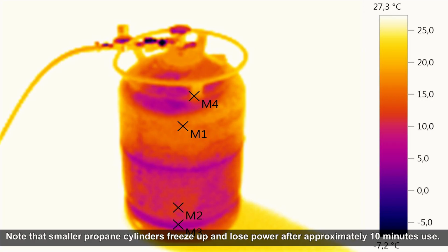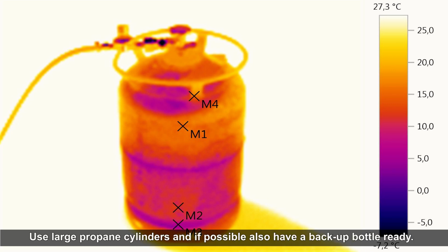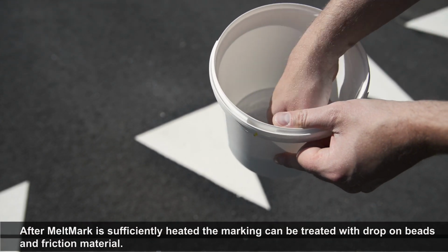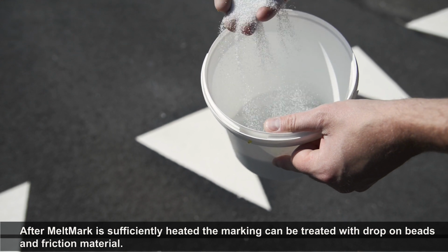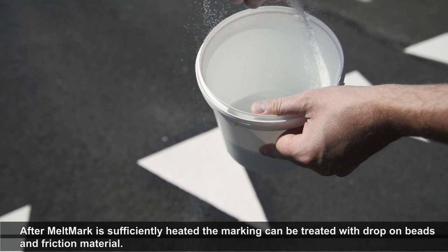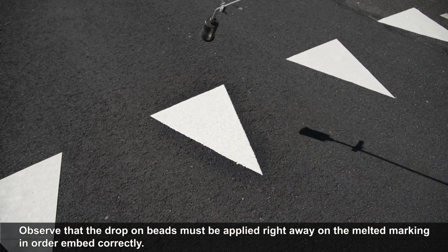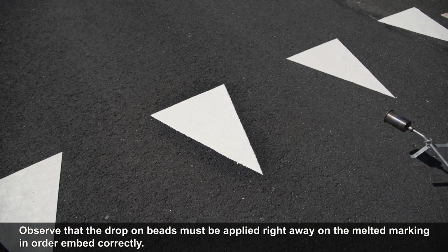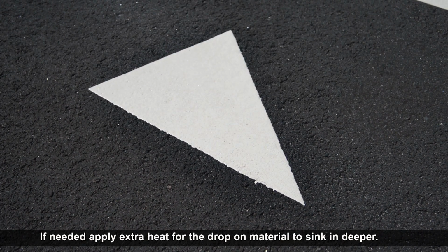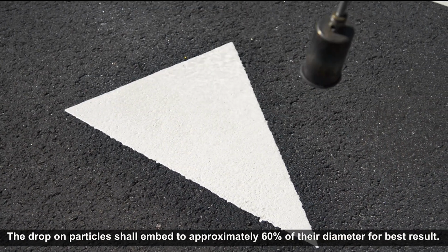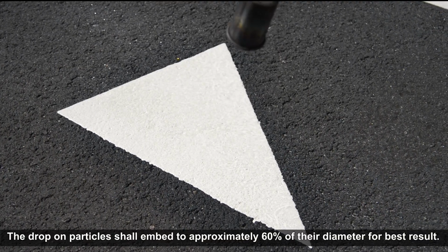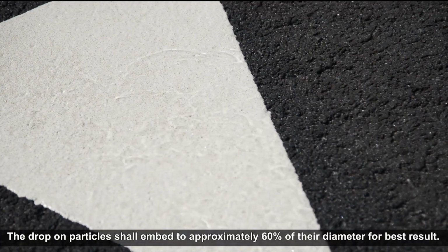Note that smaller propane cylinders freeze up and lose power after approximately 10 minutes use. Use large propane cylinders and, if possible, also have a backup bottle ready. After MeltMark is sufficiently heated, the marking can be treated with drop-on beads and friction material. Observe that the drop-on beads must be applied right away on the melted marking in order to embed correctly. If needed, apply extra heat for the drop-on material to sink in deeper. The drop-on particles shall embed to approximately 60% of their diameter for best result.